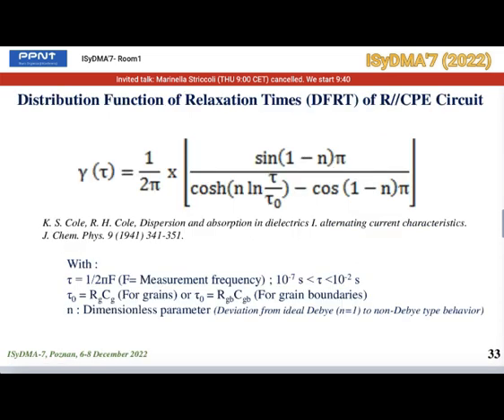Now, the distribution function of relaxation time, or DFRT, gamma of tau, of an electrical RC parallel circuit is given by this rigorous analytical formula as a function of tau, tau 0 and n, with tau equals 1 over 2 pi f, where f is the measurement frequency. Tau 0 is the RC time constant, and n the dimensionless parameter.